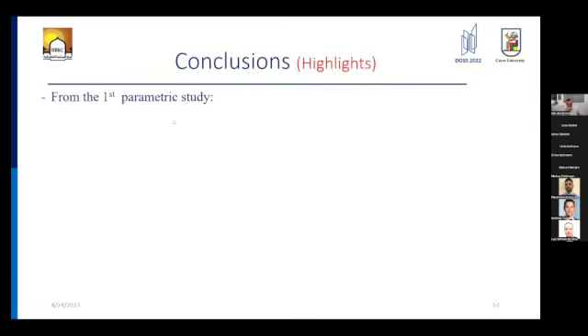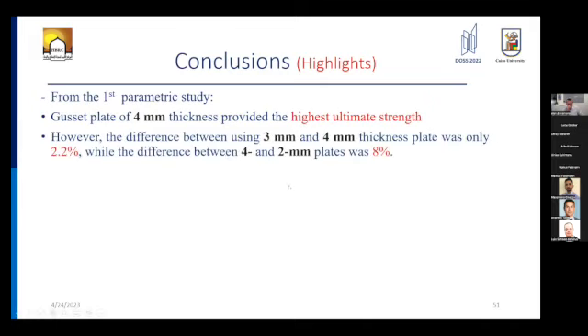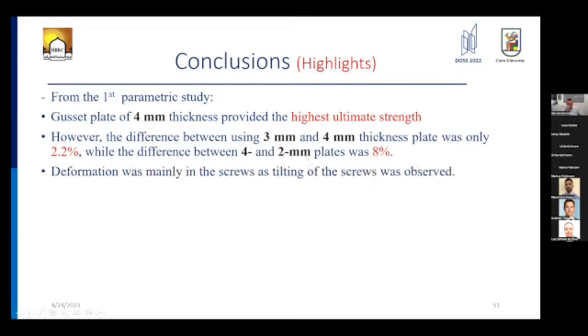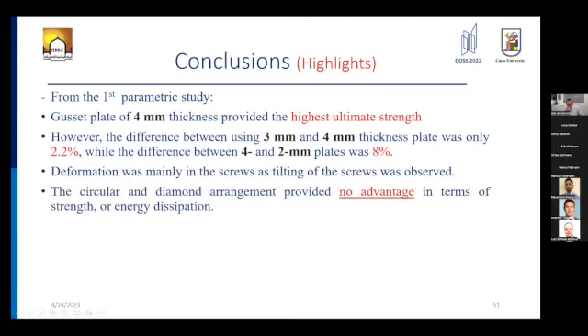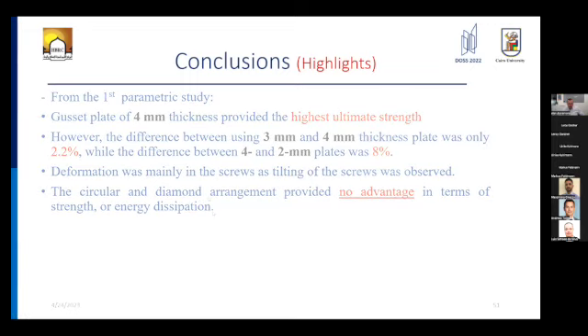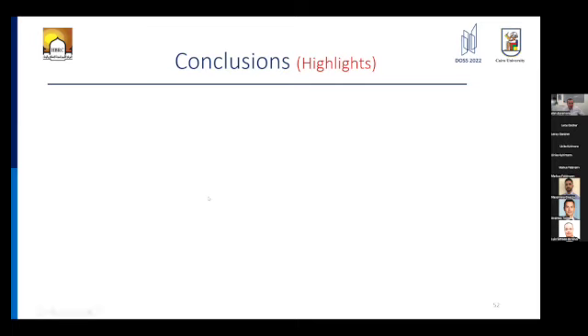Finally, the conclusions. From the first parametric study, increasing the gusset plate thickness wasn't very efficient, especially because the failure mode was tilting of the screws. So changing the gusset plate thickness wasn't very effective. The screws were more critical. And this is actually true for all types of models that we modeled: the circular and diamond arrangements provided no advantage in terms of strength or energy dissipation.